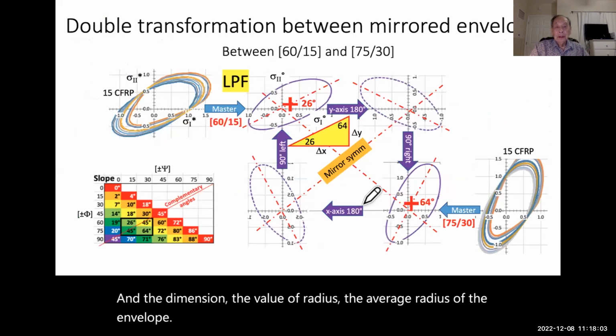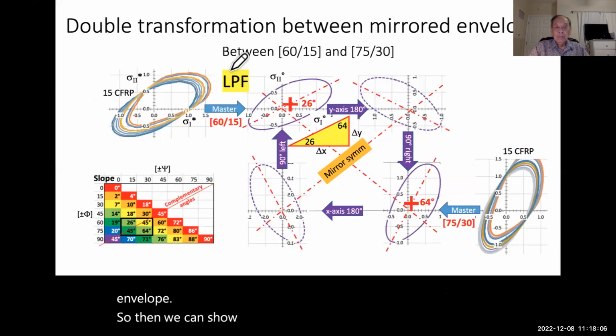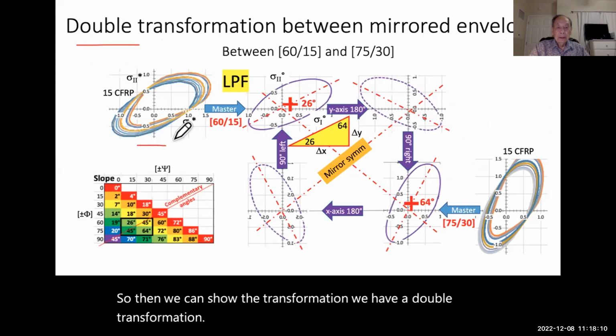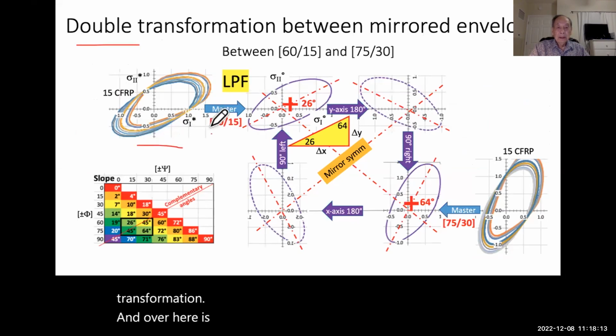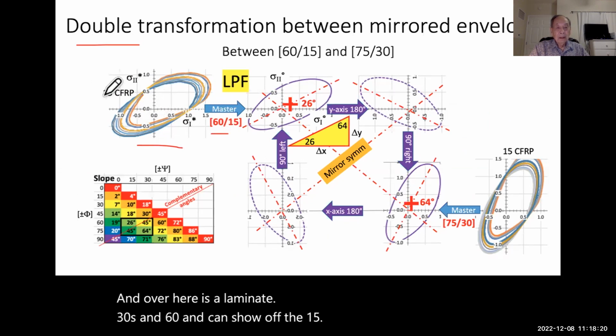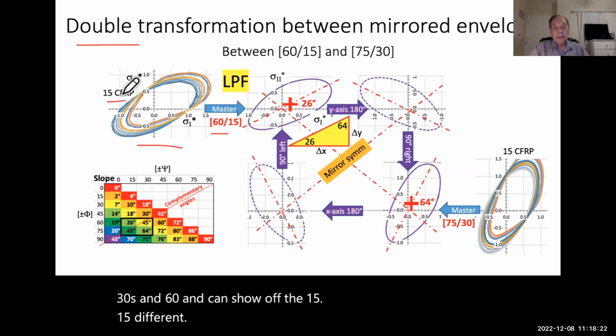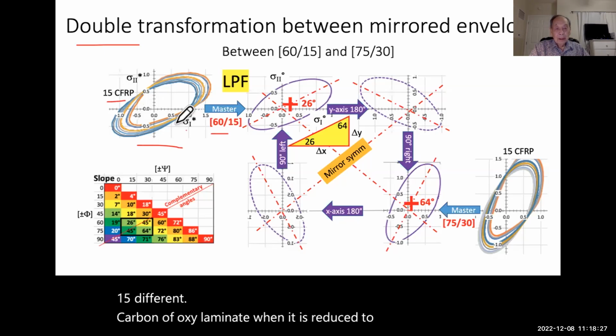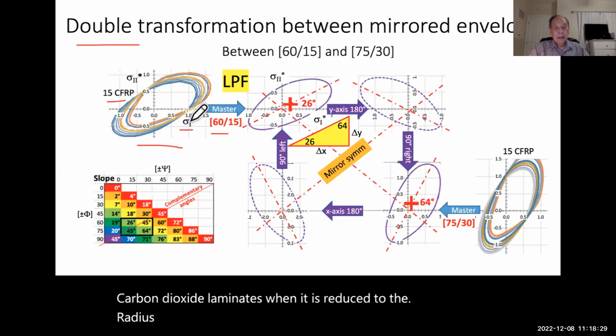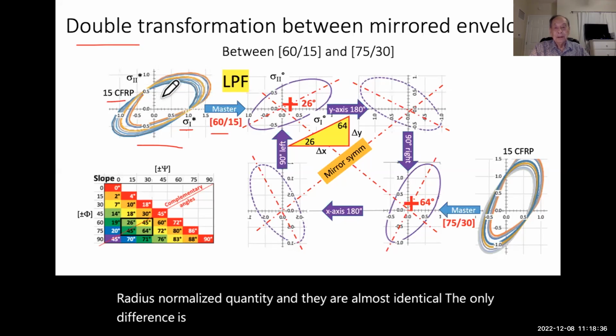So then we can show the transformation. We have a double transformation, and over here is a laminate 30 and 60, and it can show the 15 different carbon epoxy laminates when reduced to the radius normalized quantity, and they are almost identical. The only difference is their position, the center location is different.